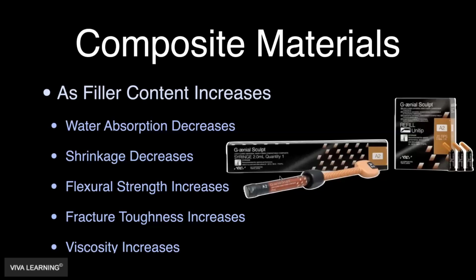Over the years, the more filler content we can put into the resin or the monomer, the higher the filler content percentage, all the physical properties of the material get better. Its water absorption decreases, its shrinkage decreases, which creates less stress on the adhesive interface. Its flexural strength increases, its ability to flex or bend increases. Its fracture toughness, or its ability to resist fracturing or breaking, increases. And classically through the years, the negative to that has been that the viscosity increases.